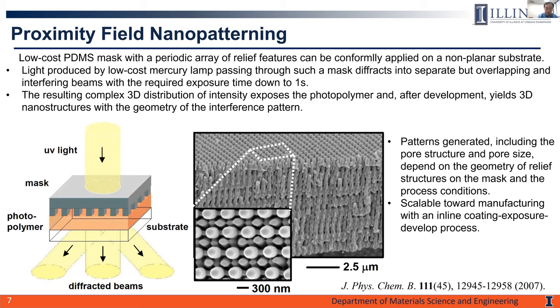But what's important is that for locations pretty near the surface of the mask, in other words, in the proximity region at the interface with the photoresist, those diffracted beams spatially overlap and interfere with one another. So we form a pretty complex 3D distribution of intensity. It exposes the photoresist, and after development, generates pretty complex three-dimensional pore structures, as shown in our preliminary data.